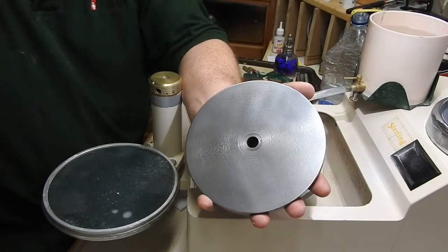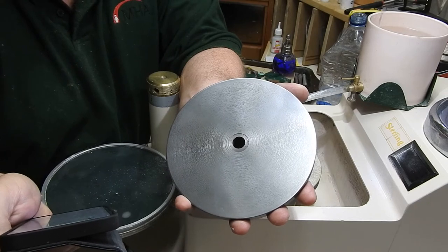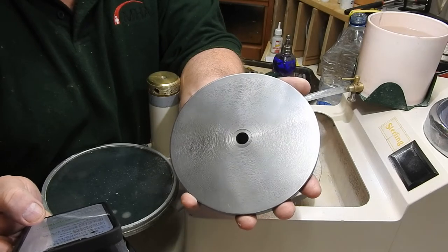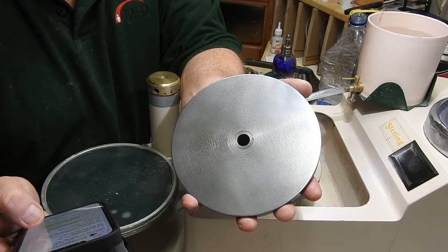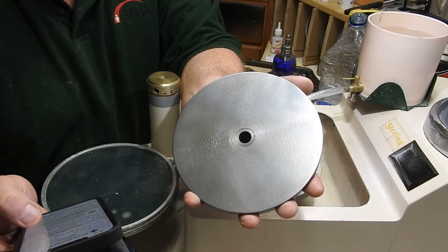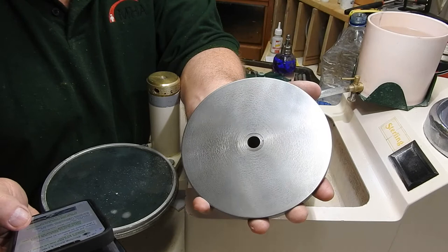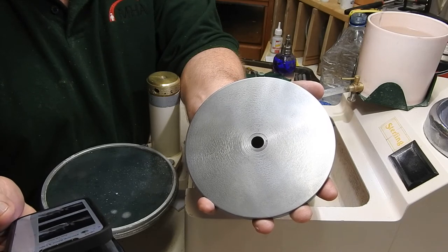So I'm just getting the information that Sandon has sent me about it. It's called the SHL, Sterling Hardened Lap, especially for polishing sapphires. It's going to last forever because it's very, very well constructed. And basically it says once you've completed on the 1200 lap, then you can move on to this hardened lap. No need for water when polishing. I said, do you use oil? Yes, you can. It's prepared like the copper lap, but you do not put the scores going through it, because obviously the way this is constructed holds the diamond powder. I think that's about all he's put on there. So we'll give it a go.